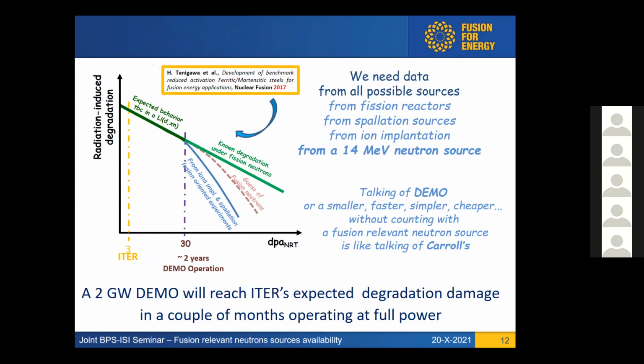So we know very well, even the simulations have been benchmarked. So we know even by computer tools to anticipate what is going to happen to materials exposed to fission neutrons. And we also know from data obtained from ion implantation, from spallation sources, from all kinds of different sources of neutrons, how can be, let's say, the worst possible scenario of degradation of a material. Our guess is that the fusion reactors will go somehow in the middle, but we don't know. We know that it correlates pretty nicely up to 30 dPa.